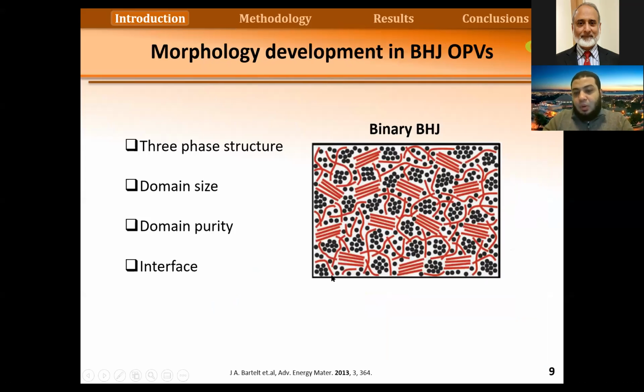So this is what the morphology looks like. We use a donor material and an acceptor material. Here the black is the acceptor material, and the red is the donor material. For this we have three-phase domains. We have pure donor and pure acceptor, and we have the interface between them. Because of this complexity, we need a specific domain size and a specific domain purity in order to have good efficiency solar cells.